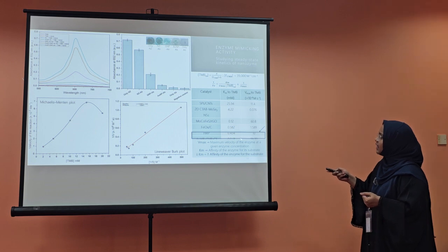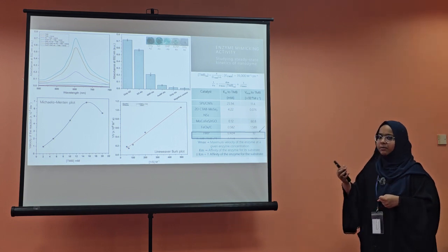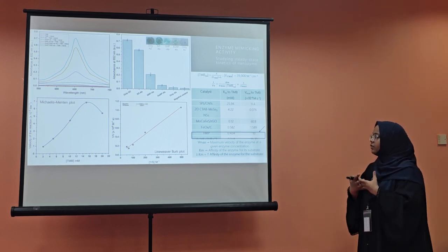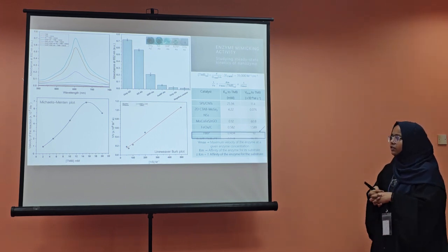As you can see here, it's slightly not visible, but it's 0.048, which is about 10 times lower than HRP, the natural enzyme. So this low Km value confirms that this hybrid nanozyme has a high affinity for the TMB substrate. Similarly, the Vmax value was about twice that of HRP, confirming that the enzyme has a high velocity at a given concentration. So this experiment confirmed that the proposed hybrid nanozyme had good peroxidase-mimicking activity.